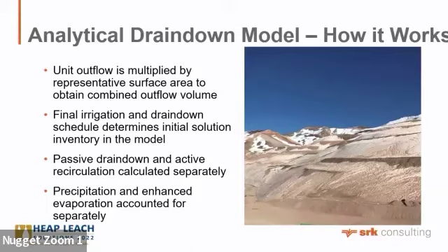And the final irrigation and the drain down schedule essentially becomes very important because it determines the initial solution inventory in the model. It does matter, so in this complex case, which phase was irrigated last does matter. It matters tremendously, for various reasons.